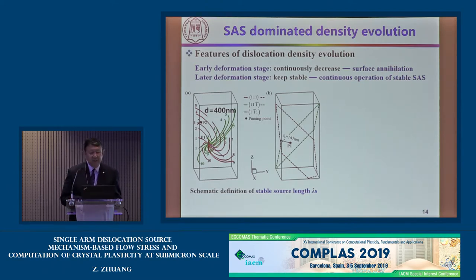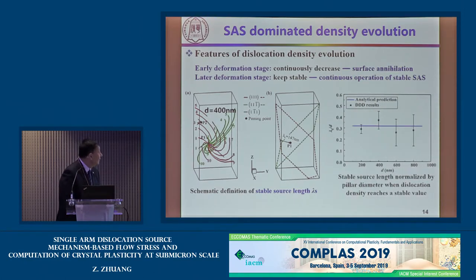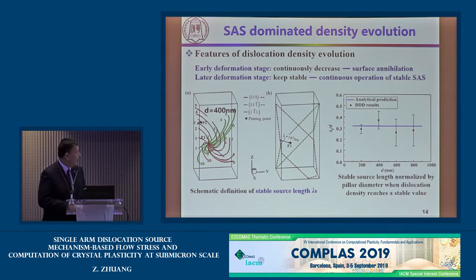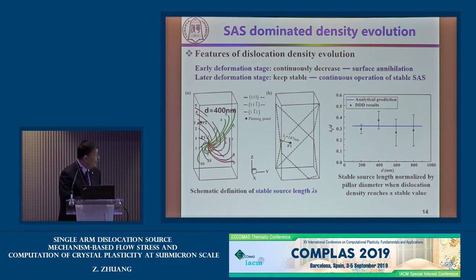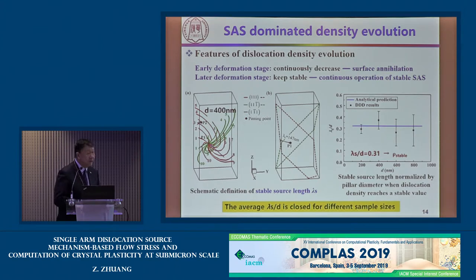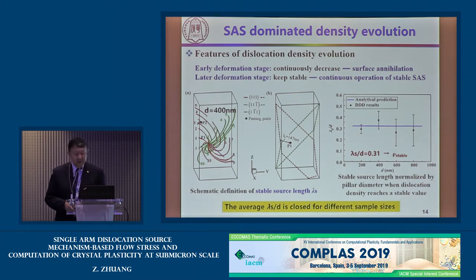We also think about how some dislocation pinning points cannot escape from the free surface and stay inside. From our calculation, approximately 150 nanometers is the distance between a pinning point and the free surface on the slip plane — we call this lambda_s, the stable source length. Corresponding to pillar diameters from 200 to 1000 nanometers, we have different values of lambda_s over D. Lambda_s over D equals 0.31, which we call rho_stable.